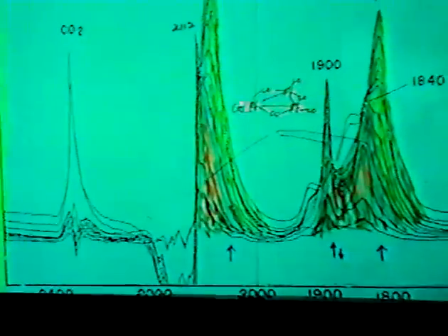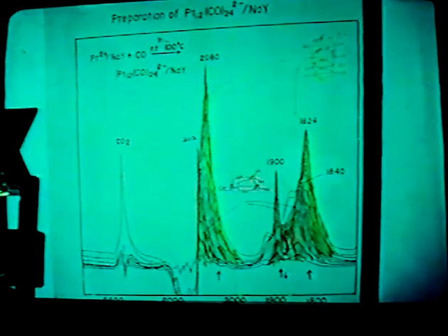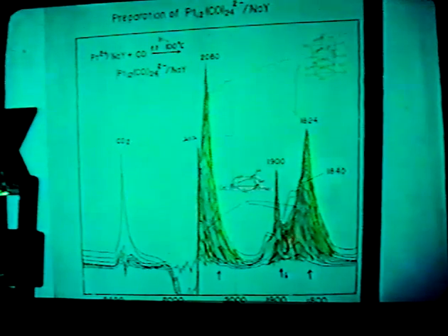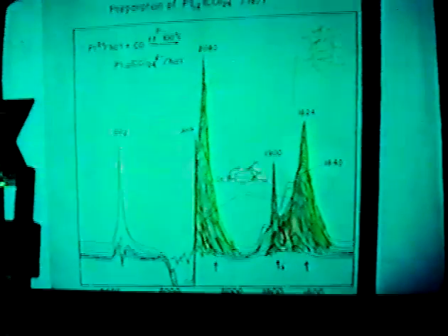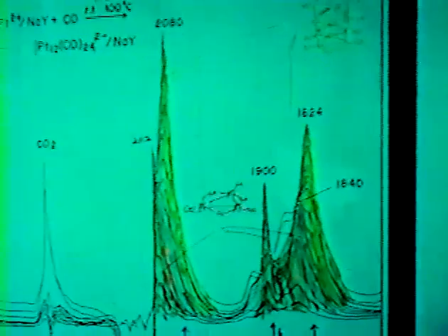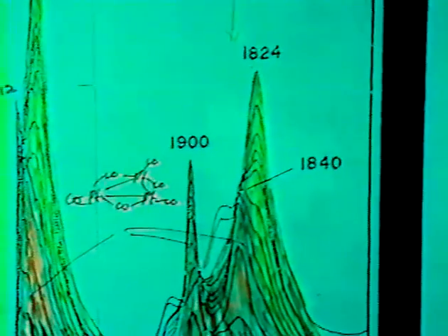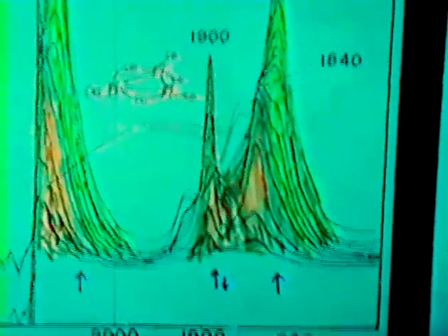We found a particular intermediate species forming with triangular platinum-platinum bondings coordinated with carbon monoxide, giving bands at 2080 wave numbers for one carbonyl, with 1900 and 1824 for the other carbonyls. This species is organized step by step up to the stacking clusters, framed with platinum 12 carbonyl 24, giving the respective carbonyls.